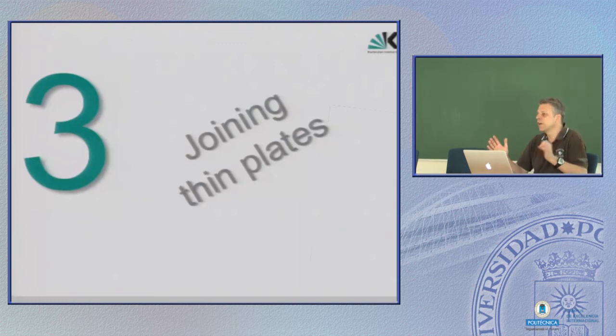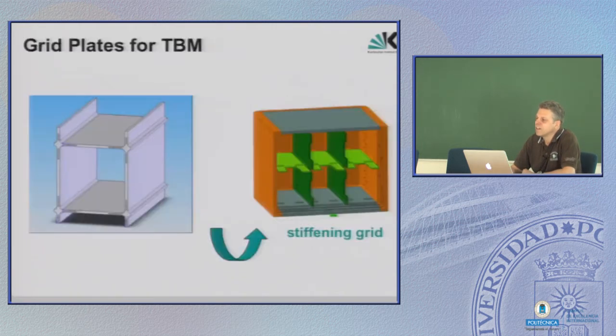Now we have the U-bend with a lid and on top and bottom the caps. Now let's come to the internal structure of these blankets. There has to be produced a grid. This grid is also internally with even more tiny cooling channels. So these are delicate plates, and they also have to be welded together in order to form grids, which means you have to perform the weld line all on these cross sections here. And again, internally there are many delicate channels.